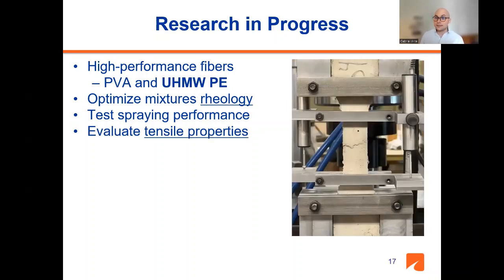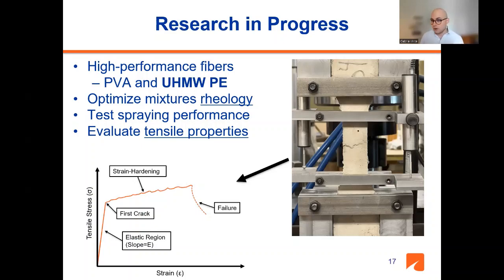Also, we evaluate tensile properties, and I'm showing this test because this is not a very conventional test that is used. This is a uniaxial tensile test, which is based on guidelines of the Japan Society of Civil Engineers. And from this test, you can obtain all the relevant properties of the ECCs. You can measure the elastic modulus, the first cracking, evaluate the strain hardening behavior, and again, obtain all the relevant properties of your ECCs. And finally, we're going to do field tests of this technology and hopefully successfully repair some of these culverts.